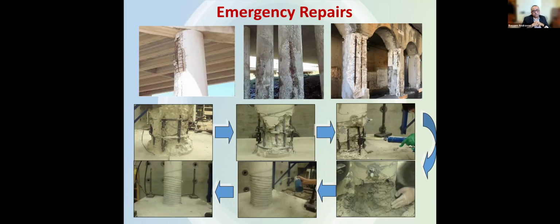So we had one of our bridge columns that were tested in our lab, severely damaged. Two of the rebars even were fractured. So we coupled it with actually two couplers here. We injected epoxy in the cracks. We applied fast-setting mortar, and then we wrapped it with SMA at the plastic hinge zone.